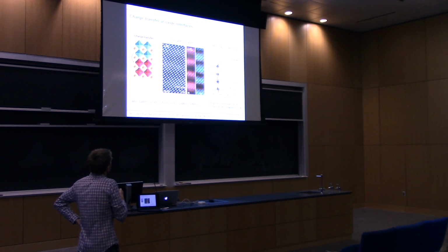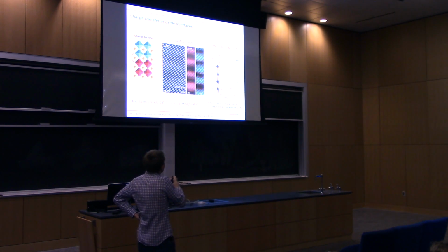So there's many examples of this: LAO/STO, titanate superlattices, the manganite superlattices I just alluded to. Here's an example that I think is a relatively clean example. Lanthanum manganite, lanthanum nickelate. Away from the interface, this manganese and this nickel is nominally 3+, right? But at the interface, what happens is that there's this charge transfer. The manganite gives an electron over to the nickel, and at that interface, you get nickel 2+ and manganese 4+.